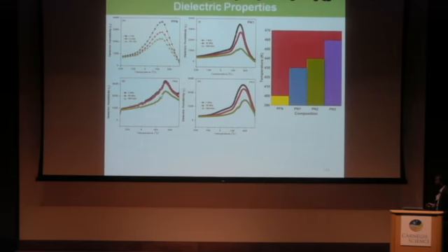So this is the dielectric property, in order to prove the ferroelectric phase transition of all the composite structures. This is the dielectric spectra of PFN, PN1, PN2, and PN3. Here, as the magnetic content goes on increasing, the ferroelectric phase transition temperature Tc goes on increasing, and all these compositions show relaxor behavior.